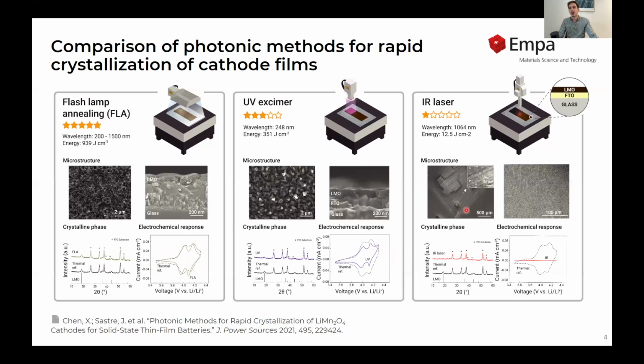In contrast, in the IR laser annealing process, we didn't observe the crystallization that we expected, and also no electrochemical response. With the UV excimer, we observe crystalline peaks corresponding to the LMO phase, but the electrochemical response is not as good as the thermal reference, probably because of lack of thorough crystallization.